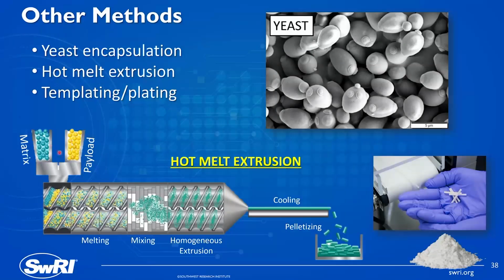So we're taking our matrix and our payload, something you might use with melt spray congealing, but in this case maybe a higher melting, passing it through a melting and mixing zone, and you get a nice filament out. Very similar to 3D printing, if you're familiar with benchtop home FDM 3D printing. You take that filament, you can break it up into little rods, or you can grind it down. And so you may not have spherical particles, but now you have payload particles of your active ingredient within a matrix. There's also templating and plating, so taking existing particles and absorbing in an active ingredient, similar to what you might do with yeast.